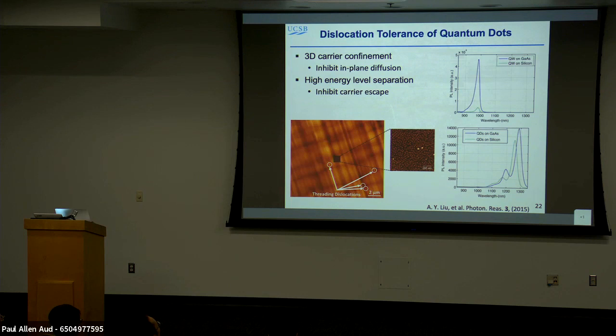So why are we and everybody else doing quantum dots when for the first 20 years of this field everyone grew quantum wells? Here's the answer. If you look at quantum wells in gallium arsenide, they look quite bright, quite good. You grow it on silicon and maybe the photoluminescence is 10%. You've lost 90% of the efficiency.